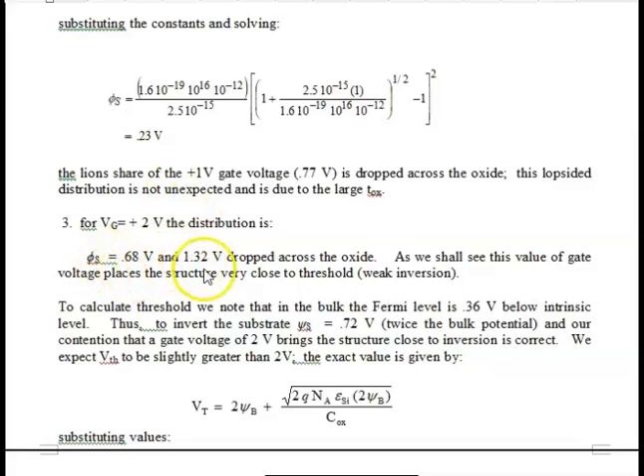And if you put in the numbers, and I urge you to do that, we get the following values. Again, these values must add up to 2 volts. We drop some of it across the oxide, and we drop 0.68 volts across the silicon. Probably easier to do the silicon first. Just put in all the numbers and we get 0.68. More than double, by the way, the value at 1 volt.